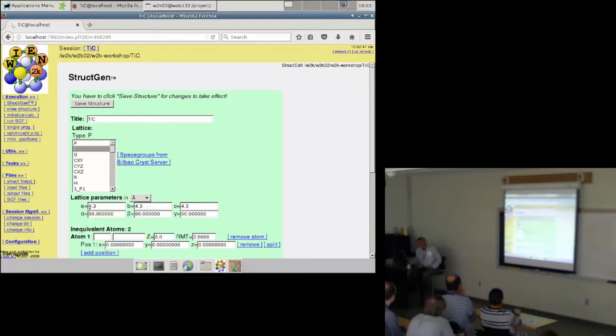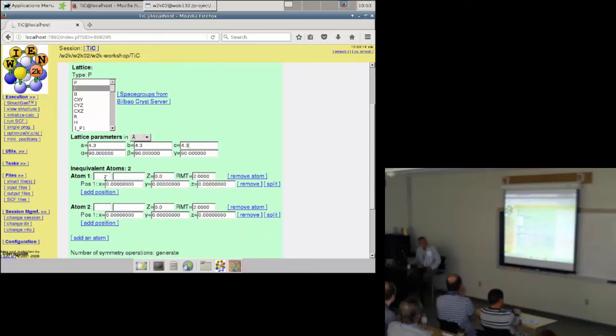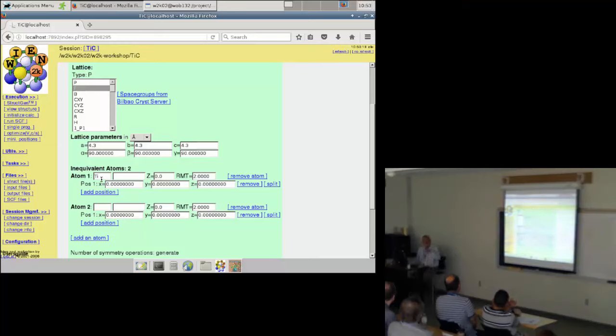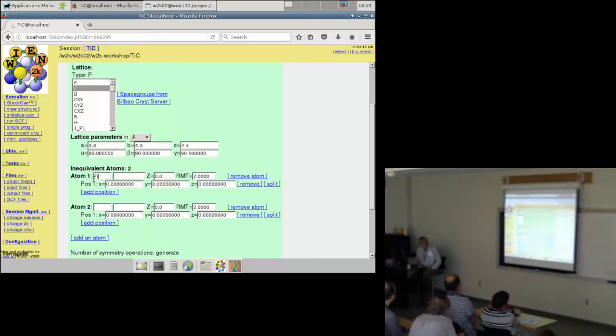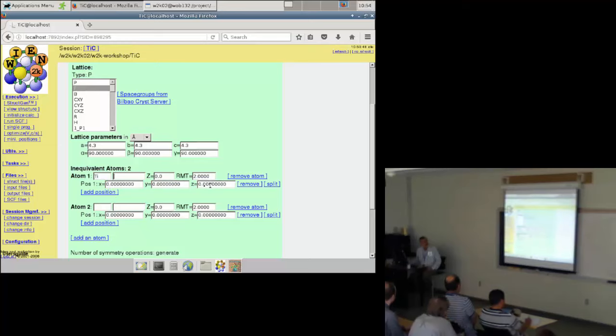Internally we always work with atomic units — bohr — so the lattice parameter of titanium carbide is about 4.3 angstrom. Most conveniently, change between input windows with the tabulator key rather than the mouse. The angles are 90 degrees. We have two atoms and all we need to specify is the name of the atom — 'Ti' — please put it in with a capital T and small i exactly as the atomic symbol. The program will not recognize all lowercase or all uppercase, so it is necessary to put it exactly like this.